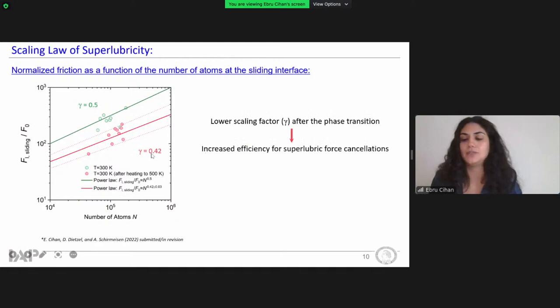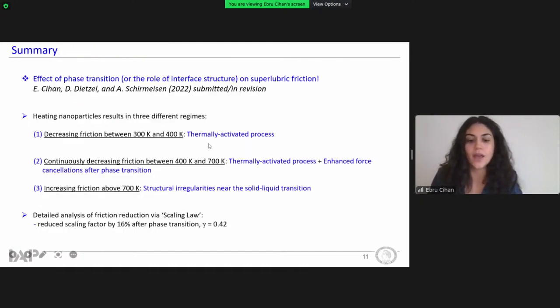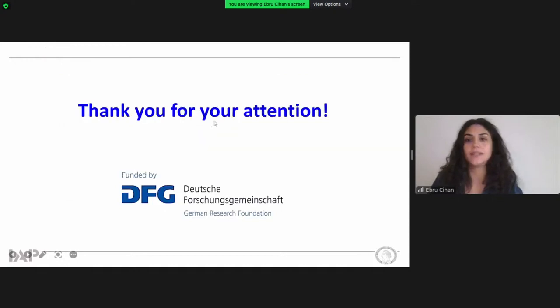And this can be attributed to the increased efficiency of force cancellations at the sliding interface, which becomes more regular due to the amorphous-crystalline phase transition in antimony. So with this, I come to an end. In summary, we tried to show the effect of direct phase transition on superlubric friction. Last but not least, these results highlight the importance of atomic structure at the sliding interface in the superlubric regime. With that, I would like to thank you for your attention.